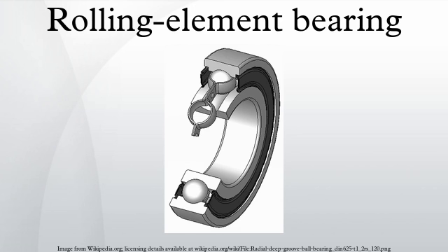The needed bearing lifetime also varies with the application. For example, Tedric A. Harris reports in his Rolling Bearing Analysis on an oxygen pump bearing in the U.S. Space Shuttle which could not be adequately isolated from the liquid oxygen being pumped. All lubricants reacted with the oxygen, leading to fires and other failures. The solution was to lubricate the bearing with the oxygen. Although liquid oxygen is a poor lubricant, it was adequate, since the service life of the pump was just a few hours.